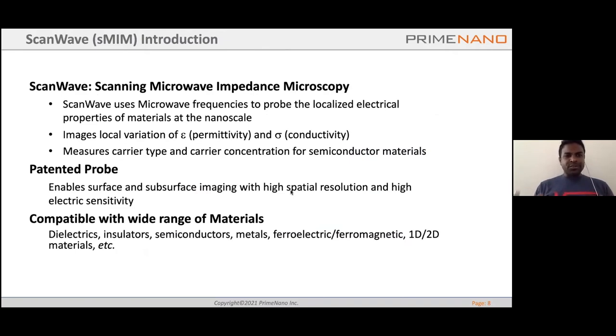So to come to the introduction about the ScanWave system, in scanning microwave impedance microscopy, we use microwave frequencies to probe localized electrical properties. Essentially, we are looking at the impedance of the system, and the impedance can be converted into permittivity and the conductivity at microwave frequencies. Now, for a semiconducting material system, we can convert this permittivity into carrier concentration and also the polarity of the carriers. For this, we have to use a specialized AFM probe, which improves the surface sensitivity as well as the spatial resolution. sMIM is done in near field, and hence the spatial resolution is only limited by the tip radius or the radius of the source of the microwave.